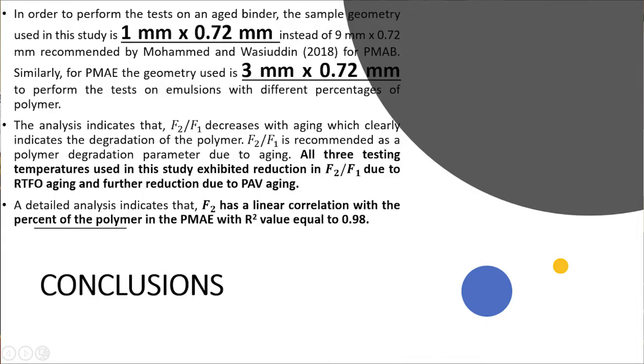We used two different styles of samples, and we have results that linearly correlate with percent of polymer. F2 over F1 reduces with aging, and this project shows that the polymer degrades with temperature and aging.